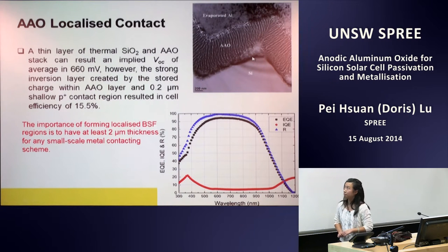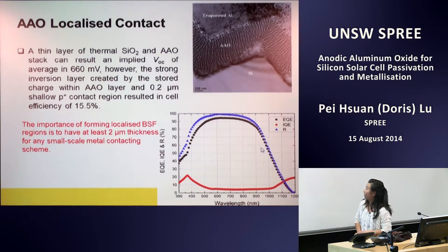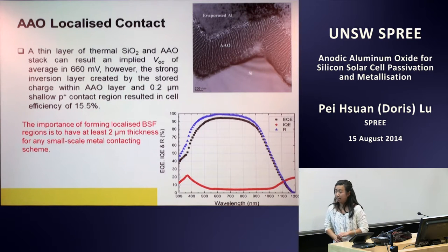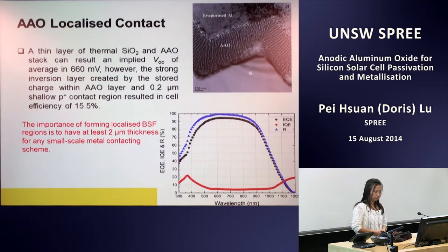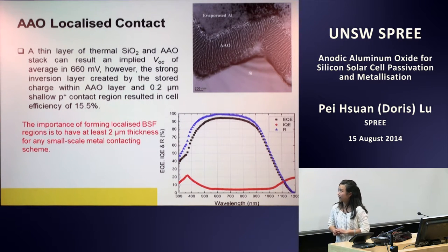only form 0.2 microns of back surface fields. This results in very poor IQE and EQE response at long wavelength. And this research leads to an important question: to form localized back surface fields with very small scale contact, you need at least a 2 micron thick back surface field to result in good efficiency.